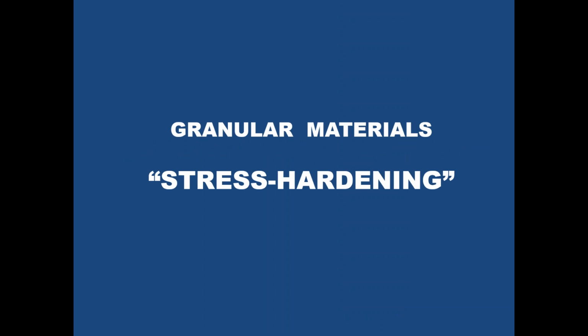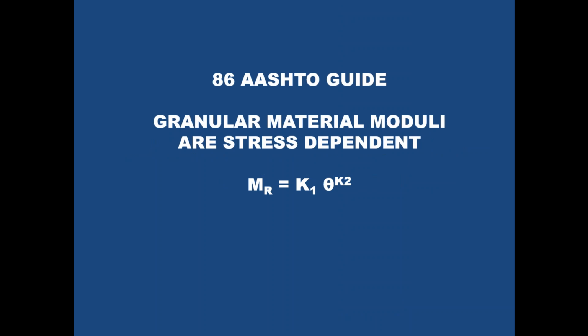Granular materials are stress hardening. Stress states go up, they get stiffer, and thus they have a peculiar behavior. The 86 guide picked up on some work that Gary Hicks did at California with Carl Monismith for his thesis on resilient modulus testing of granular material. And this particular model, K1 theta to the K2, was developed, and it's one I still like and use. I think it captures the major effects. You can add some things in if you'd like, but nevertheless, this does capture the impact of the stress state, which is theta, the bulk stress.